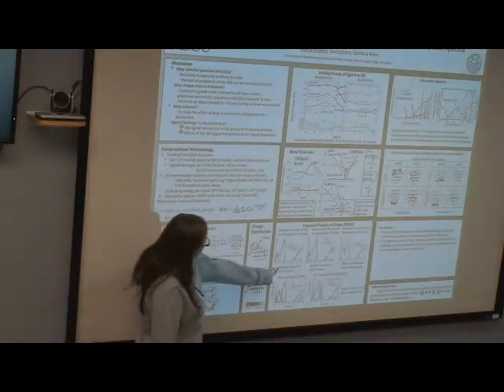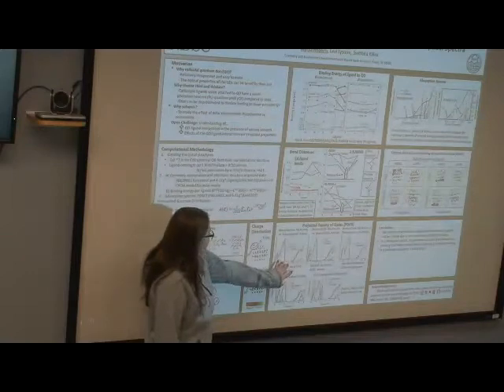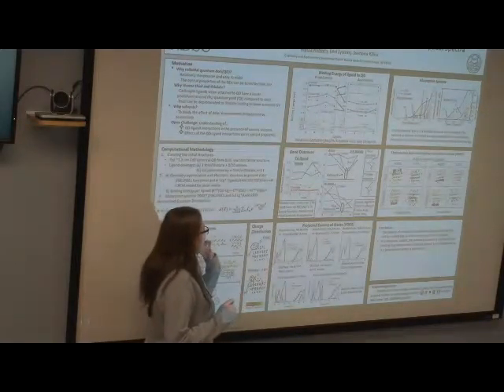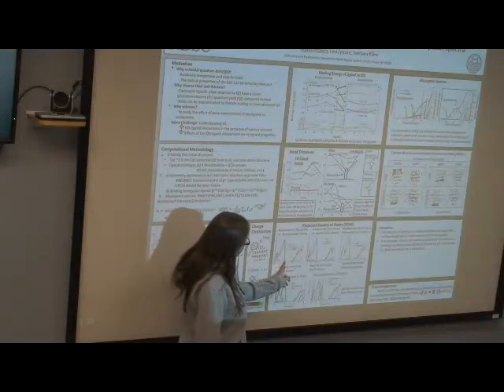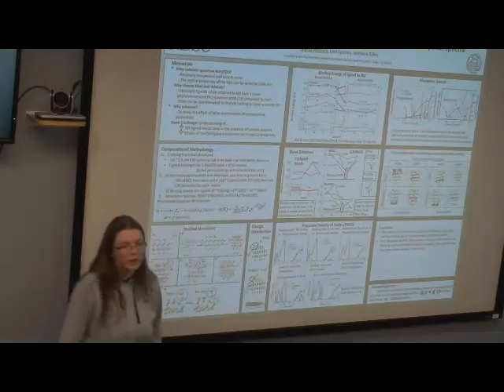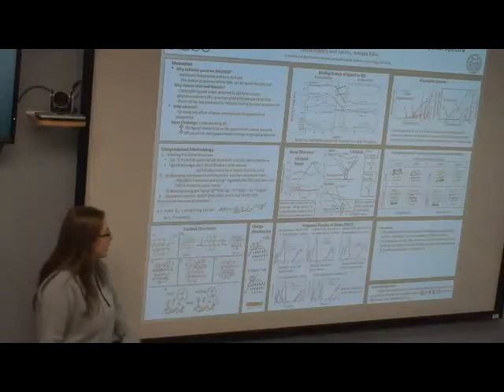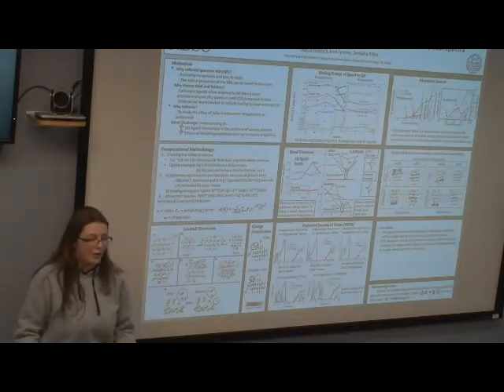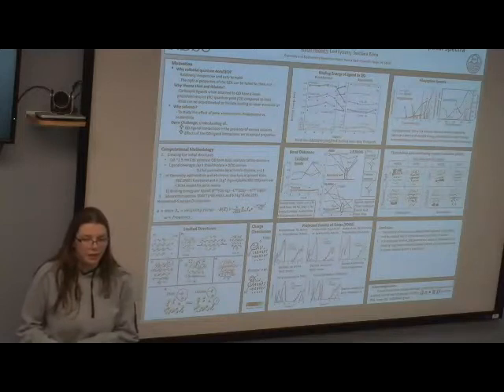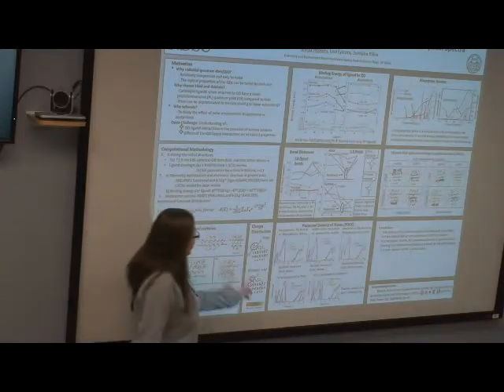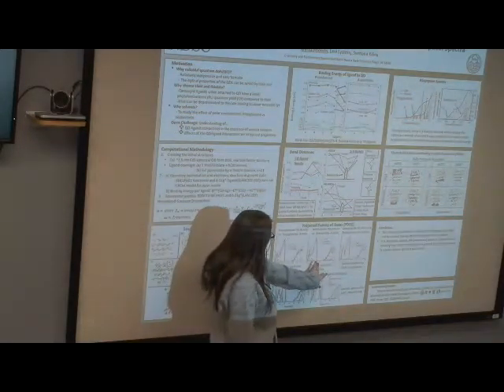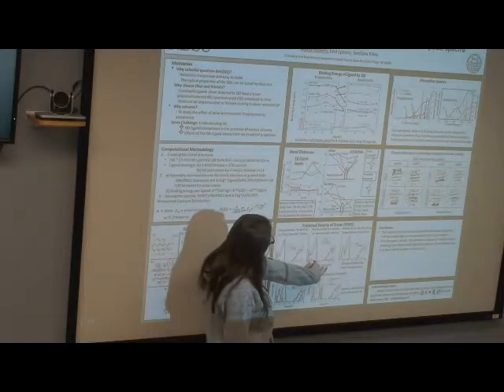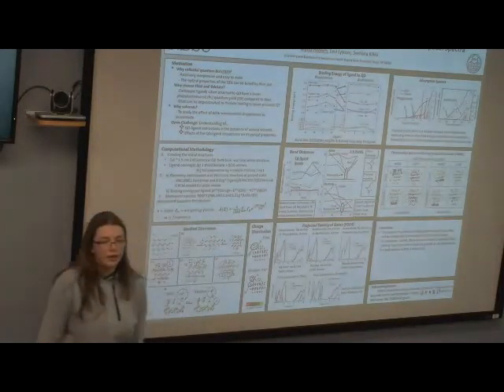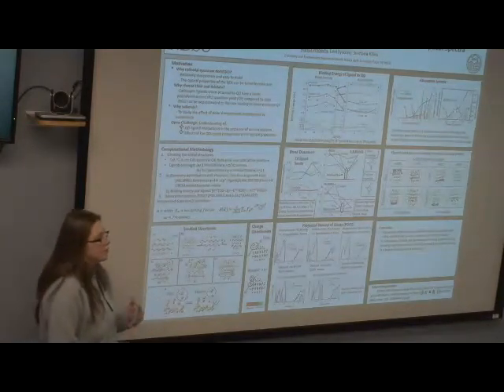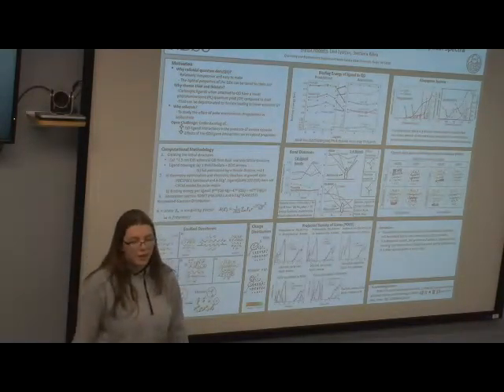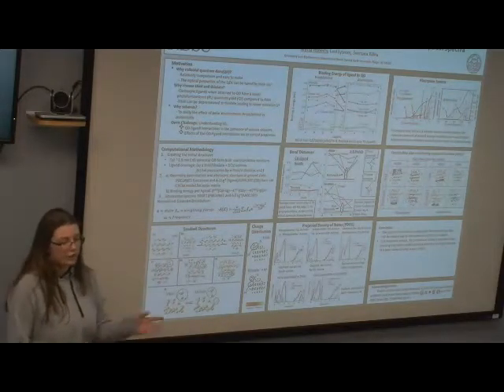So in this one, you can see that with no amine and propylamine, the distance moves up further towards the quantum dot, which could potentially create a trap state if there was more than one thiol. So it's showing the necessity for amine in propylamine. And then in this one, you can see that the no amine versus amine for acetonitrile is hardly any different. Acetonitrile does move it closer to the band gap, but it's not super dramatic.